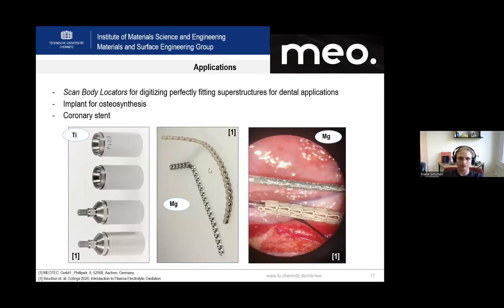Here we have one implant which is placed into your body. The best implant is one which you don't need to remove after the operation. So you have this magnesium component inside your body. It fulfills its function, and then when your bone is good again, you want to avoid a second operation to remove the component. The human body can degrade magnesium components over some months. But maybe you need this component 30 months inside, and after 24 months your body transports it away. So you can apply magnesium oxide coatings via PEO in order to adjust the degradation time. This is one use in medical engineering.